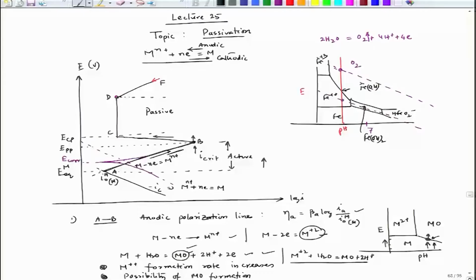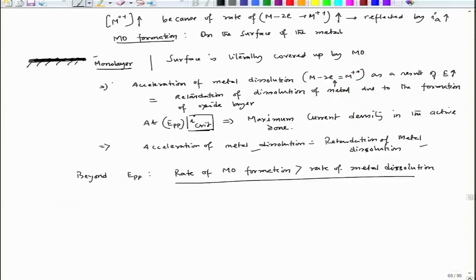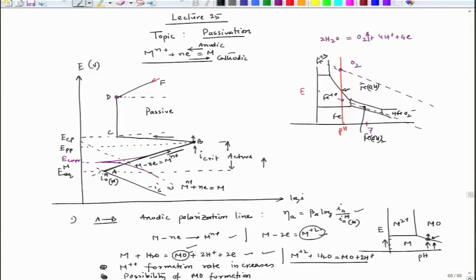the ion diffusion from the inner surface, that means the metal and metal oxide interface, to the outer surface, which is metal oxide and electrolyte. And at a certain location, I will have a situation like steady state, where the rate of oxide growth would be exactly equal to the rate of dissolution, which is nothing but I p, and this I p is I passive.